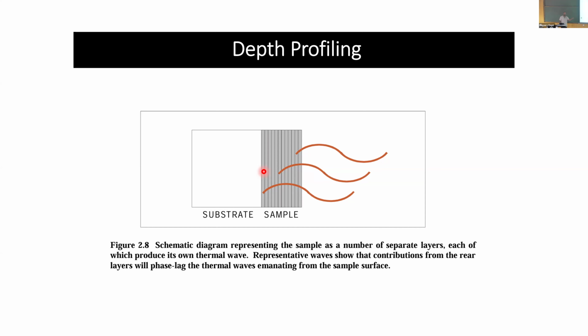So now what we can do is use this particular factor and assign the absorption to a certain depth in the sample. So let's say your sample is 100 nanometers thick, in the measurement we can actually measure the phase angle with respect to what we excite the sample with.